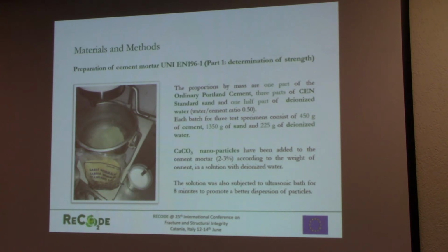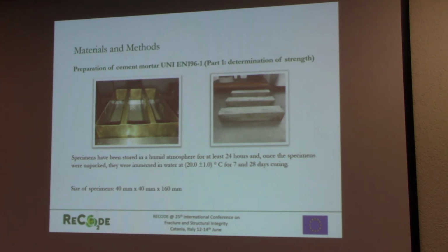We carry out a double investigation in order to understand the proper mixture design, and we investigated the solution of calcium carbonate nanoparticles mixed in water with and without the ultrasonic bath. Okay, I can skip this. The specimens are the standard mortar specimens. And we carry out the mechanical test after 7 and 28 days curing.